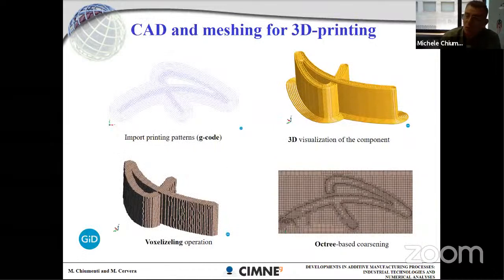Now, how do we work? What is our strategy in this case? Once again, we use G-code. The G-code represents exactly the deposition sequence to deposit the filaments. Once we have this, we go through a voxelization of the full component, and after the voxelization, we go through an octree-based coarsening. At the end of the day, we have a very well optimized mesh, where you have elements where necessary, and all the rest use a very coarse mesh.